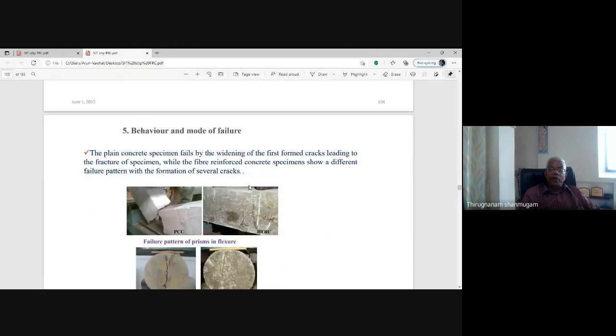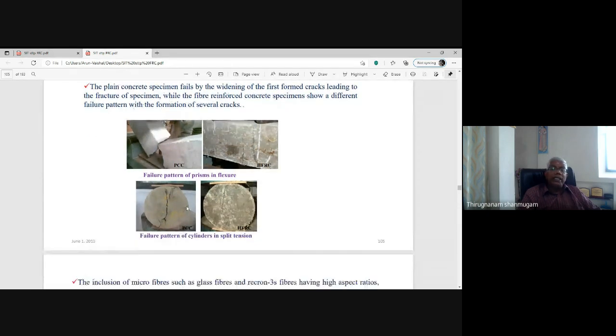The mode of failure, this is a conventional prism splitting into two pieces, but here there is no splitting action, only the crack is produced. Similarly, in the split tensile test, a vertical crack is developed in ordinary concrete, but here there is no vertical crack, only hairline cracks are available.